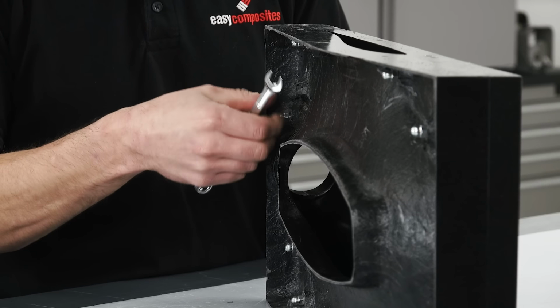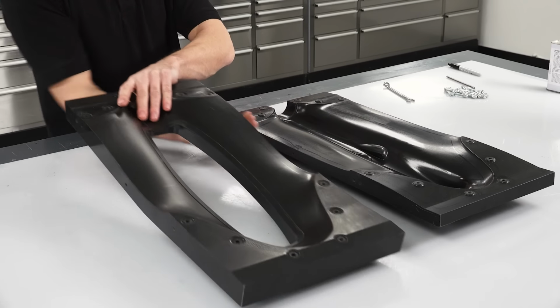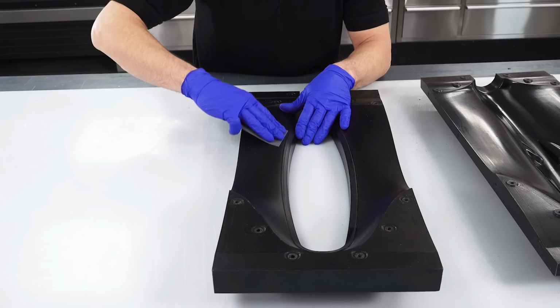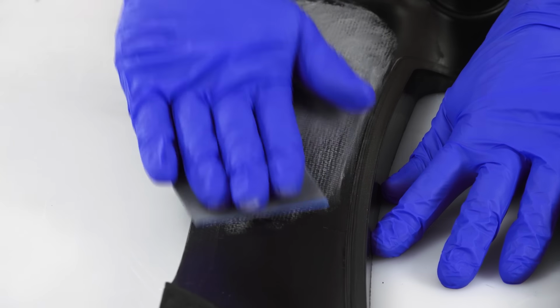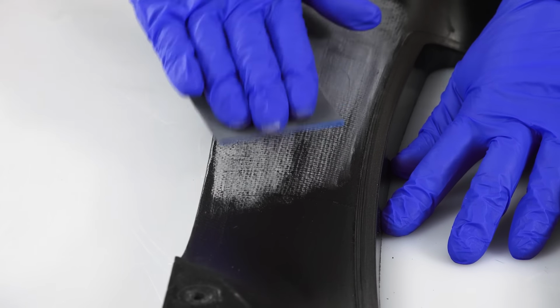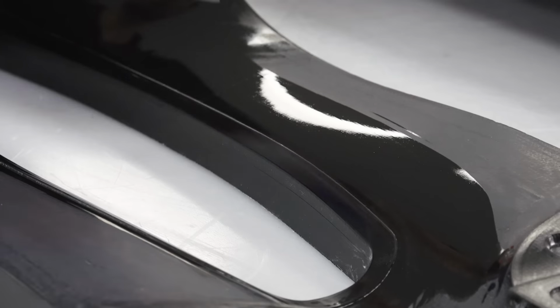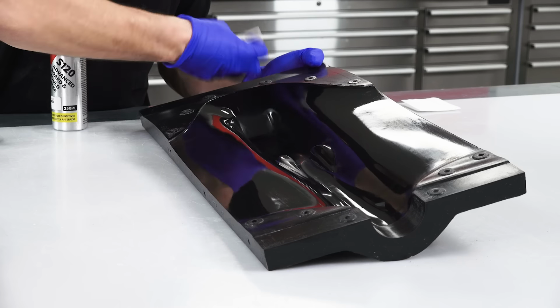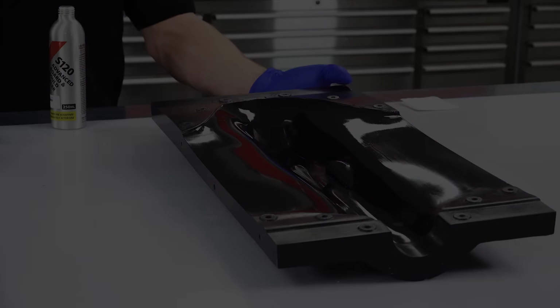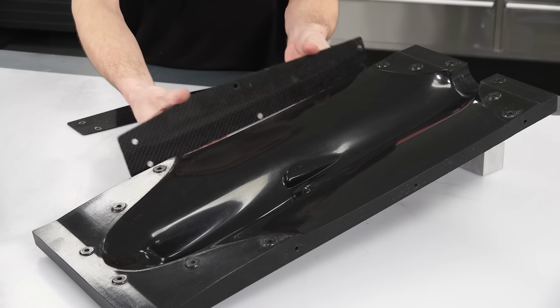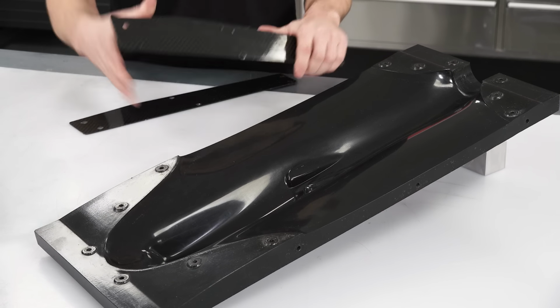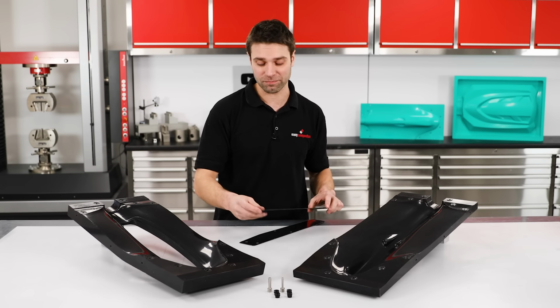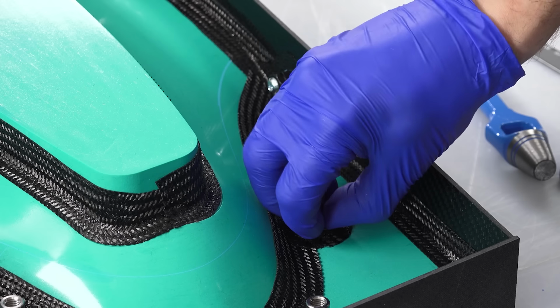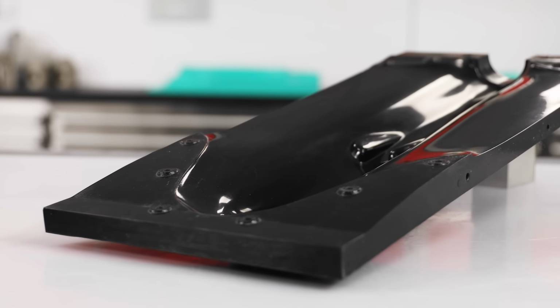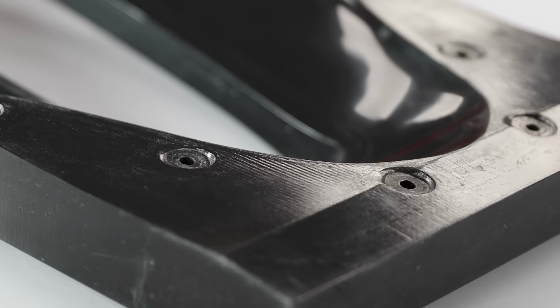After the post-cure, you may notice that you have a small amount of print through caused by the elevated temperature of the cure. In order to remove this, you simply flat it down with an 800 or a 1200 grit abrasive and then apply 1 or 2 coats of S120 to restore the gloss. With the addition of these side plates, which have simply been machined from carbon fibre sheet, we now have a complete set of moulds. And by using the XT135 tooling prepreg and the MB6 bushes, we've managed to achieve a really high level of finish and accuracy.